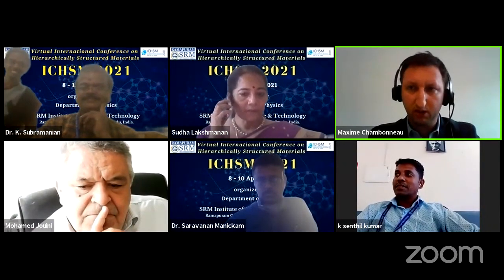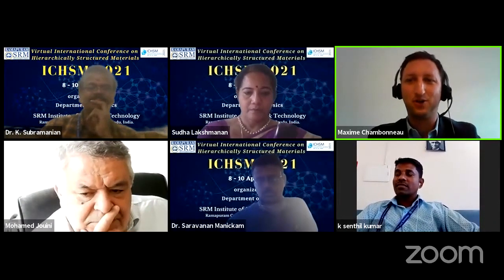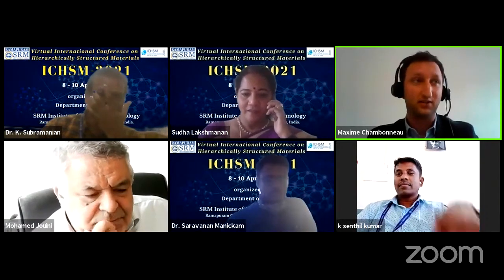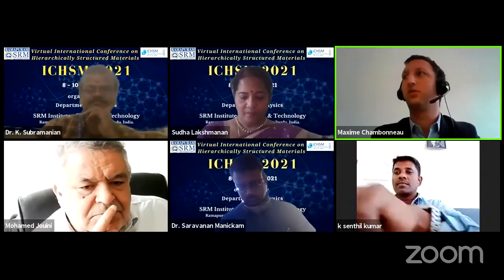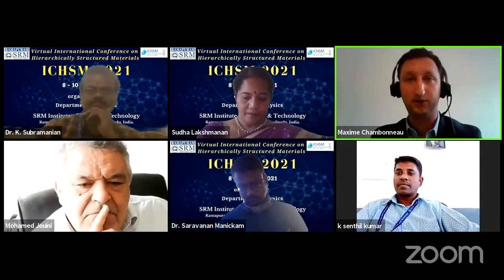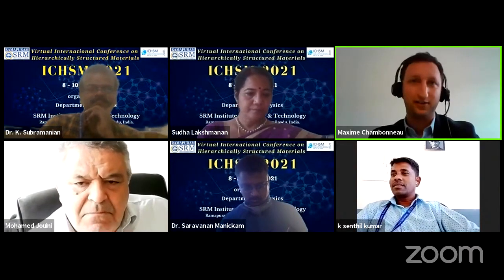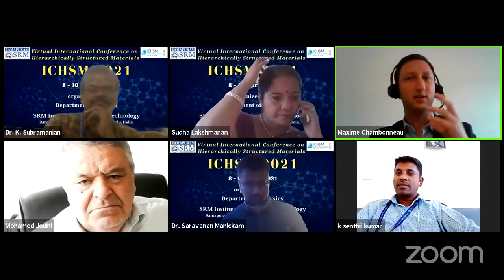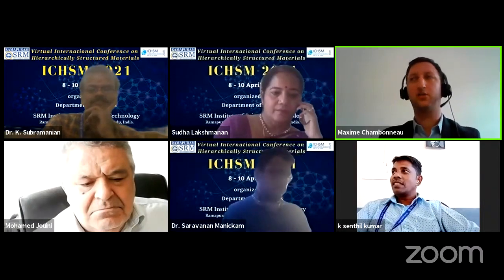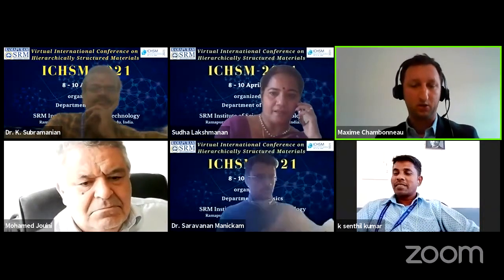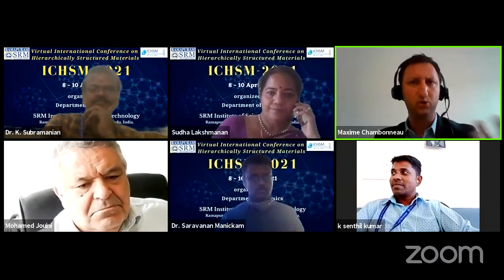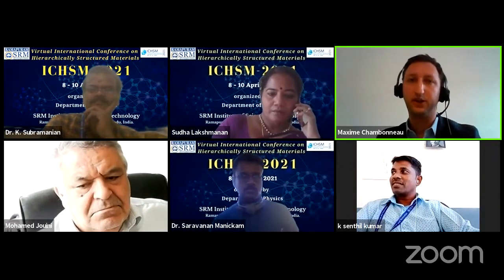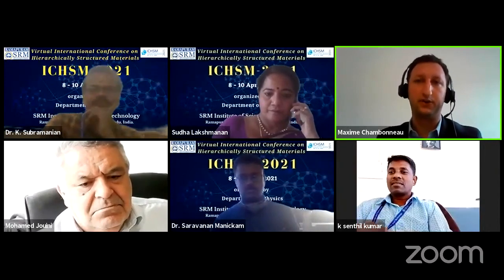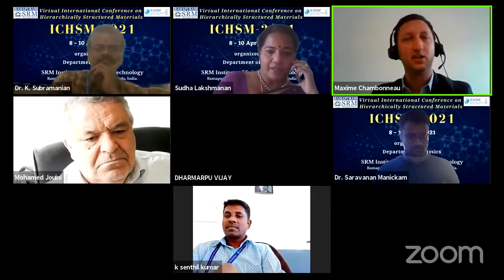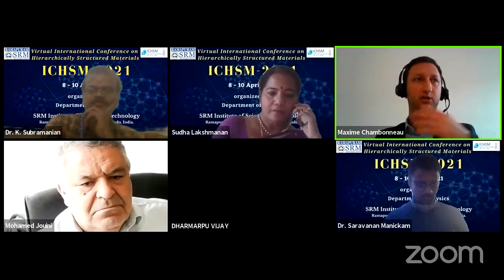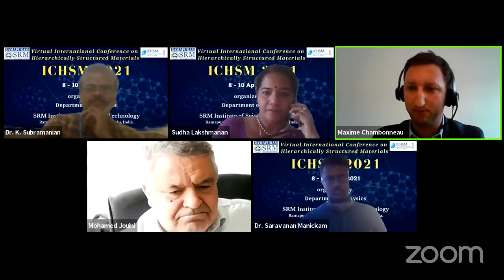And concerning your first question, what are the lowest losses that are achievable? Well, to date, these 4.5 dB per millimeter are the lowest losses achieved in silicon with the laser inscription technique. As I said before, you can check the publication of Professor Michal Lipson, working in New York, who works on SOI, so silicon on insulator, and of course they achieve much lower losses. However, the SOI technique, as I said, is not that convenient. It is really powerful, but we've got to find some alternative, and this is the philosophy of my work, actually.